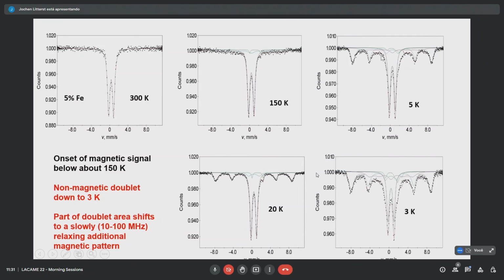And in addition, what we see developing is some extra line, that's some divalent contribution, which is smeared out. And if you look at the asymmetry of the lines, it goes to the other side completely if you go to low temperatures. You have an additional pattern in there, which is slowly relaxing. It's not the fully developed field as we see for the cluster, but it's gradually growing at the expense of the doublet. The doublet is still non-magnetic down to the lowest temperature, but we have the onset of magnetic correlations.